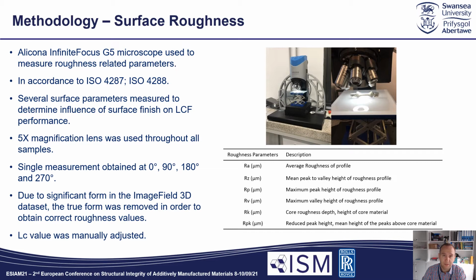Prior to testing, to understand and quantify the surface roughness profiles of the different surface finishes, an Alicona Infinite Focus G5 microscope was used to record the roughness related parameters, each of which are defined in the table below. So several parameters were measured, so we can identify which of the parameters appear to have the greatest influence on fatigue performance. So for this analysis, a 5 times magnification was used throughout, with single measurements recorded at intervals of 0 degrees, 90 degrees, 180 degrees, and 270 degrees. So every quarter turn around the specimen, to give us a full picture.